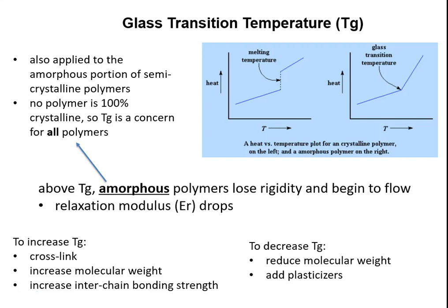So that's a really big thing to look for if you have especially a polar polymer like nylon. It can absorb moisture. The moisture will act as a plasticizer, give you a lot more free volume between chains, and while it might not show up at a zero-time instantaneous mechanical property, it could reduce Tg and show up at temperature.